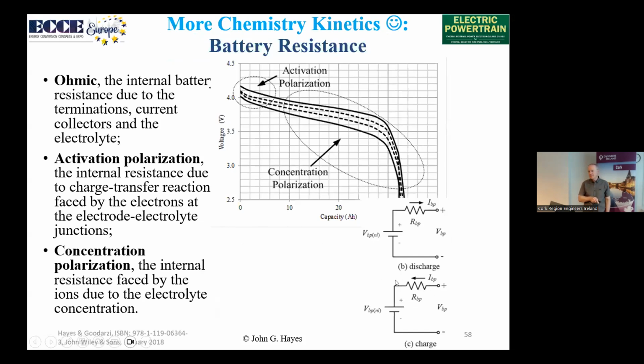But I can't let this voltage go above 4.2 volts because I'm going to damage the life of the cell. I can't pump high current in there because it's so cold. I'm also going to get lithium plating and the resistance. So I need to gently heat it up to drop the resistance. Now, I'll show you an example of that in a moment. So I need to simply raise the temperature of the pack and put in current with time. But a lot of what we put in initially is simply to raise the heat.